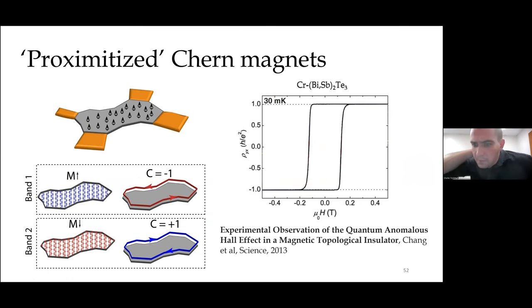So this system, of course, is not very different in principle from these proximitized Chern magnets, from these doped films of topological insulators. But the important difference is the presence of these magnetic dopants. Because the surface is sprinkled with these magnetic dopants with very high magnetization, the contribution of the chiral edge state to the total magnetization is very small and isn't nearly enough to overwhelm the total magnetization of the system. Whereas in twisted monolayer bilayer graphene, because it's an intrinsic Chern insulator with a small total magnetization, the chiral edge state's contribution can be dominant and indeed can change the sign of the total magnetization.